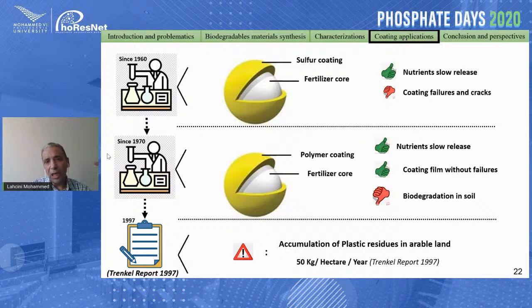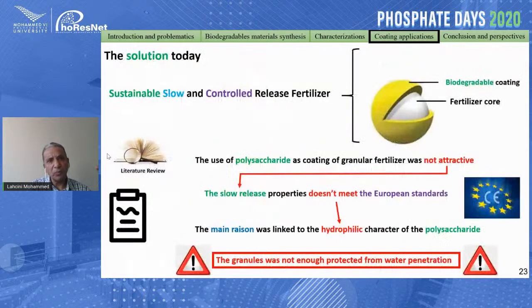They are used for slow release because of high barrier properties, high mechanical properties, and also their hydrophobic character. But unfortunately, this material is not biodegradable, and after fertilizing, its accumulation in soil degrades the quality of the soil. It was reported that about 50 kilograms per hectare is accumulated in soil every year when we use this type of fertilizer.